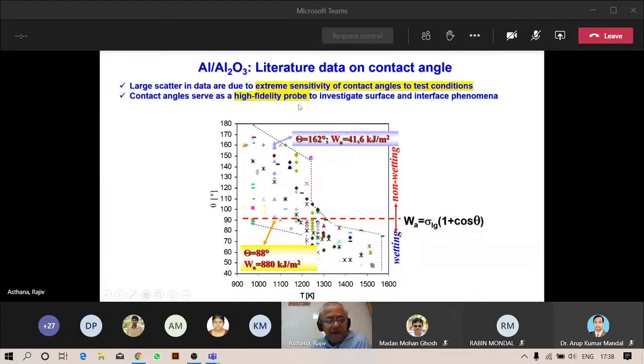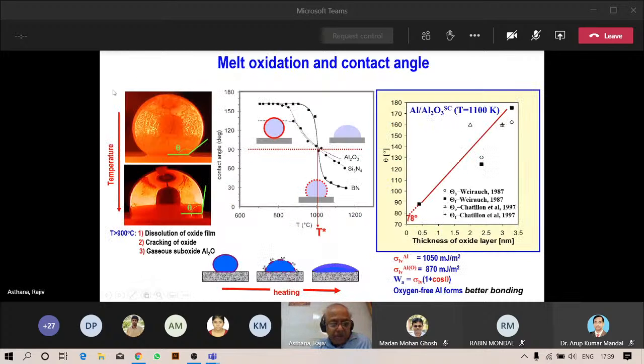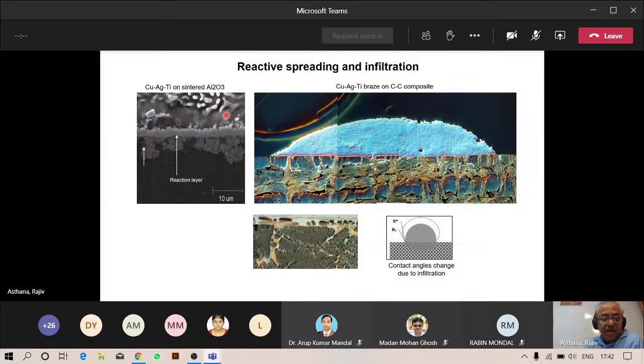So again, we're looking at the effect of melt oxidation on contact angle. If you have a thin oxide skin, the angle is very large. But if you raise the temperature under vacuum, the angle will drop because the oxide will partially disappear. Typically, above 900, it's not fully sintered, fully dense, so it has some porosity in it. And during the wetting test, you can see that the liquid has permeated into the pores, but also formed a reaction layer. We see the same thing with composite, like carbon-carbon composite, on which we have a brazed droplet sitting. And because of porosity, some of the liquid is wicked in the pores in the carbon composite. When that happens, the volume of the liquid changes, the contact angle changes.